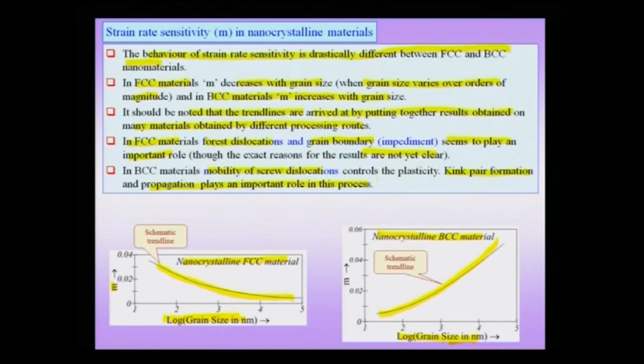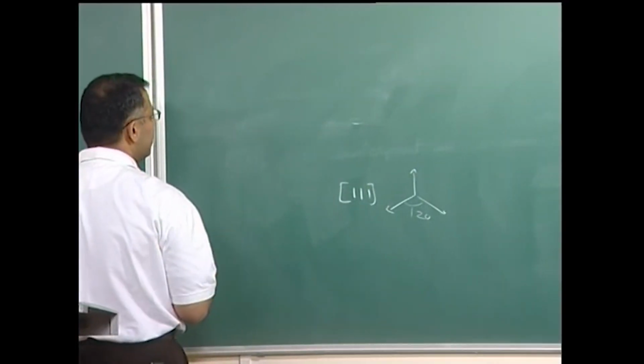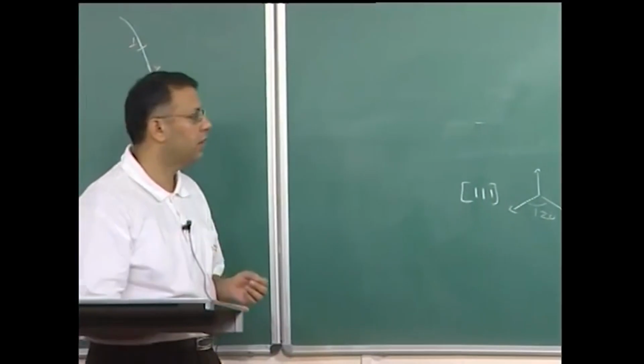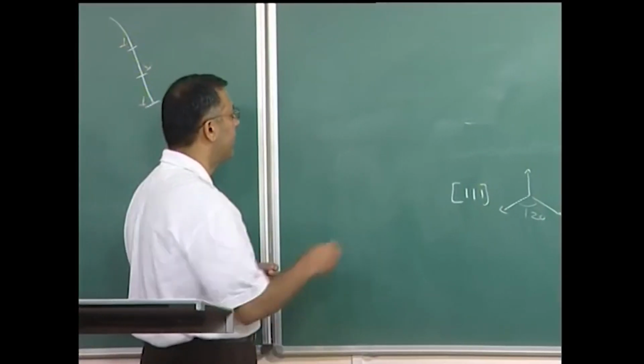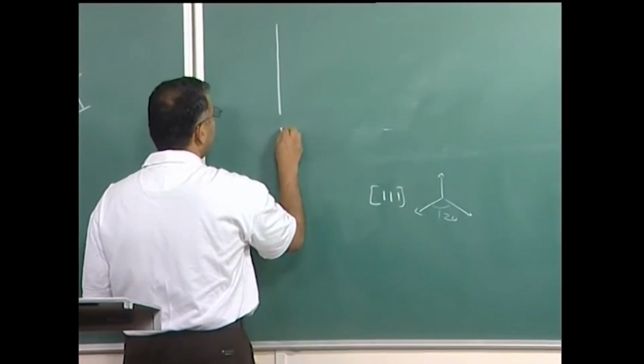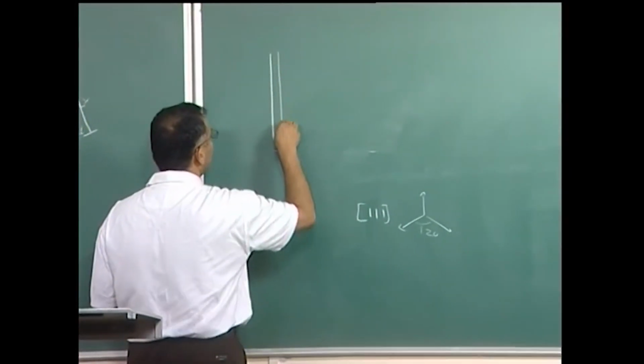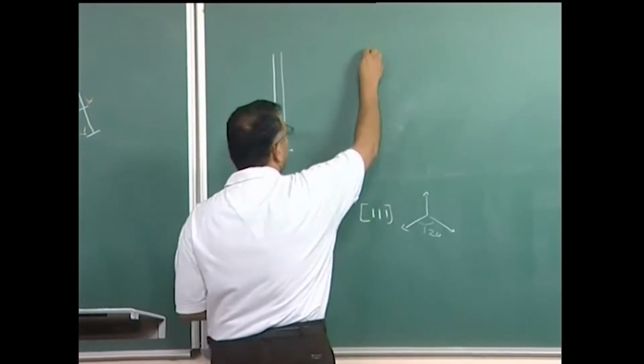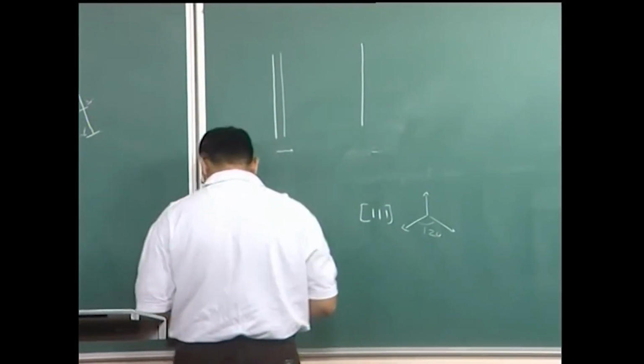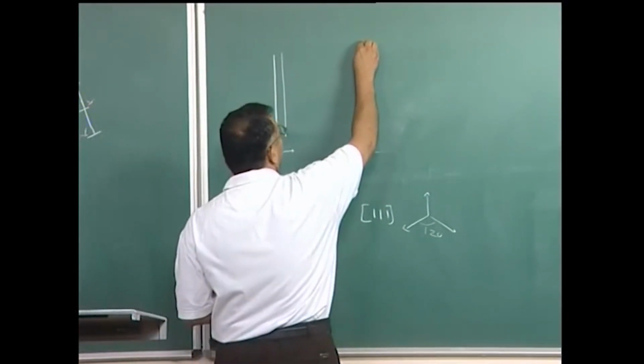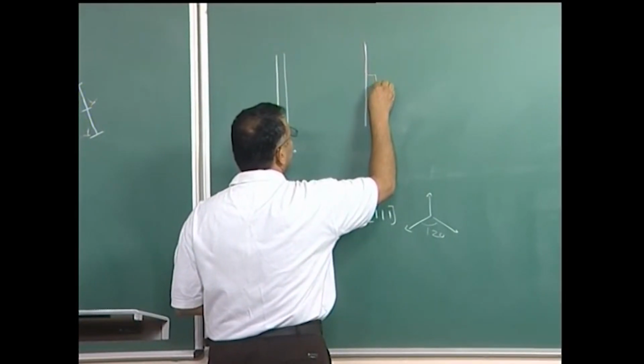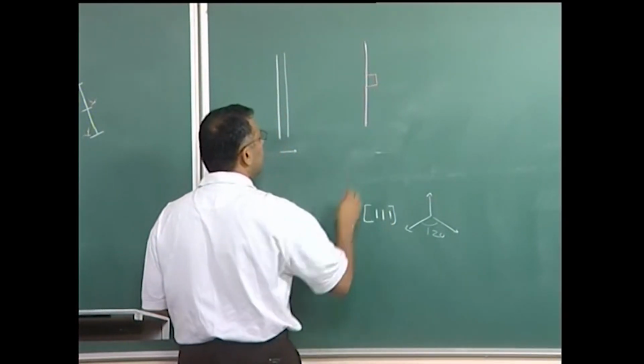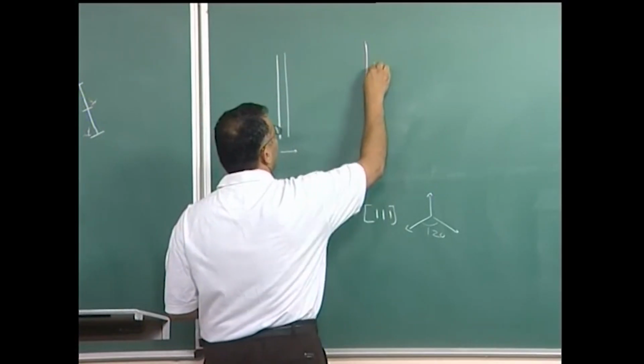So, I will briefly draw what is meant by this kink pair formation mechanism and its propagation to understand plastic deformation in BCC materials, which is also given as one of the important reasons for this strain rate sensitivity. So, if I have a dislocation line, the entire dislocation line can move by a Burgers vector and come here. An alternate possibility is that this dislocation line may actually develop a kink pair. That means, it can form a double kink like this, and then this double kink can actually propagate.